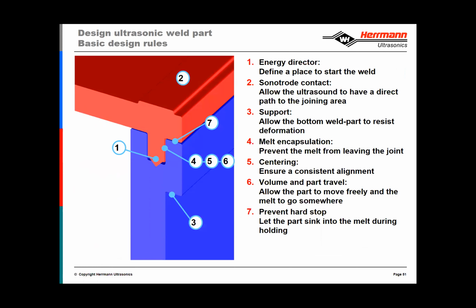Again, what we're looking for is the red part to be driven by the sonotrode, to vibrate freely, and the blue part to be held in the fixture motionless. If the parts already have a bit of a press fit in that situation, and the blue part will resonate together with the red part, then we're not creating relative motion between the parts, and this is a weld inhibitor.